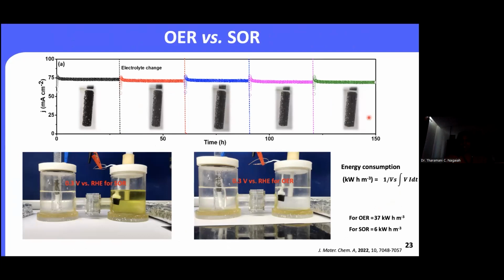However, it is very important to see whether hydrogen is still produced for a longer duration. And we are monitoring the electrode surface every 25 to 30 hours. You can see that there are still a lot of bubbles, even up to 150 hours. Here we need to change the electrolyte, because as I said, especially after 25 to 30 hours, the turbidity of the solution is increasing because of the production of polysulfide. Therefore, every 30 hours almost, we keep changing the electrolyte, and the current is quite stable.